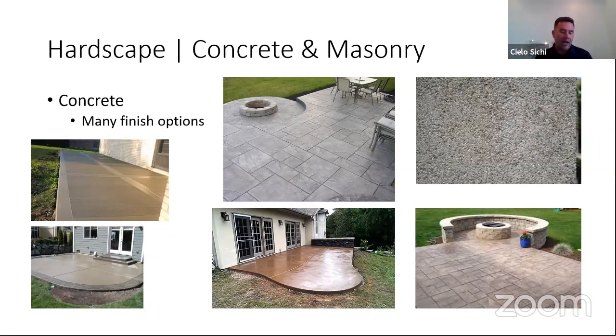I prefer a very light sand finish or a light acid wash finish, which is another way this look is achieved. You can acid wash it after it's set up, about 4 days afterwards. You can use muriatic acid at a 10% dilution ratio. So 10% muriatic acid, which is the acid that people use for pools, so 1 part muriatic acid to 9 parts water. And you can put that on concrete and scrub the heck out of it, and essentially remove the cream portion after the fact.